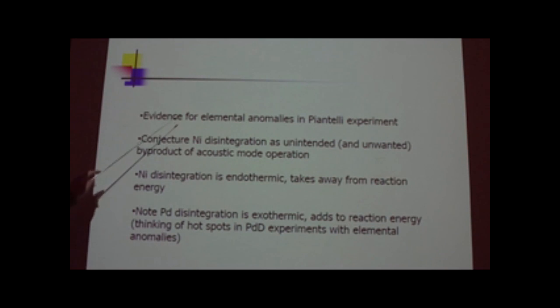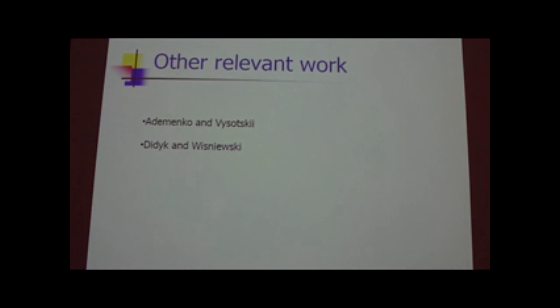So, evidence for elemental anomalies in the Piantelli experiment. There's also massive charge emission, which they observed as well. Conjecture: nickel disintegration is an unintended and unwanted consequence of acoustic mode operation. Nickel disintegration is endothermic, so it's taking away from the energy you're producing. In palladium in hot spot operation, I think that's acoustic mode operation. I think it's hot because palladium disintegration is highly exothermic, so it's making your excess heat a lot larger. And there are elemental anomalies reported in association with the hot spots in palladium.